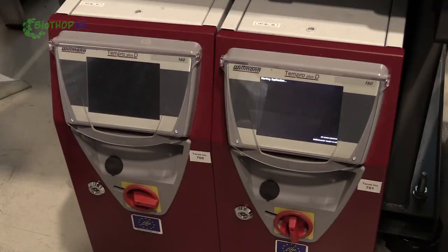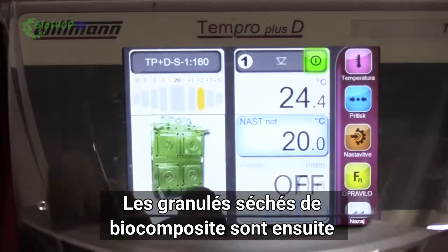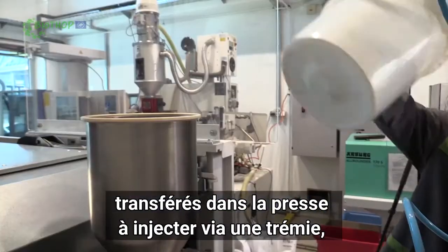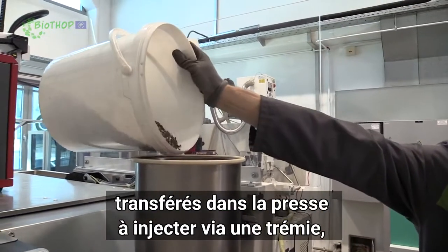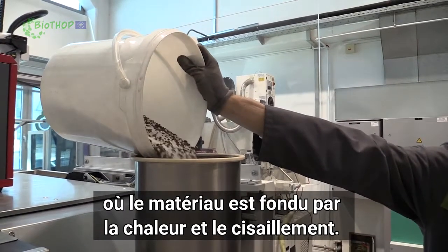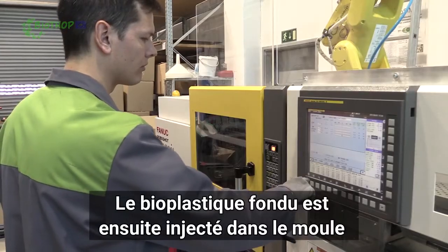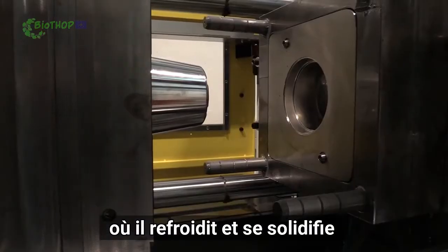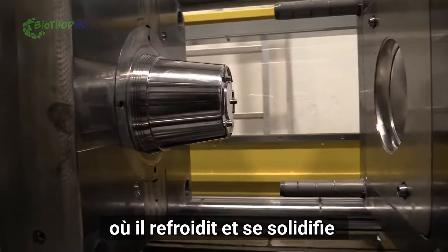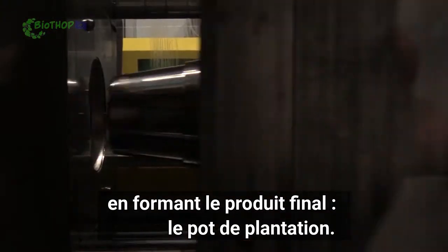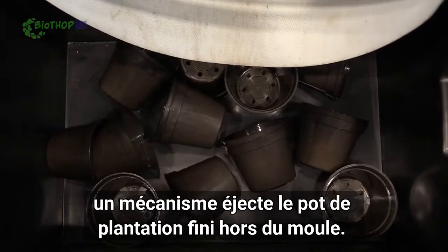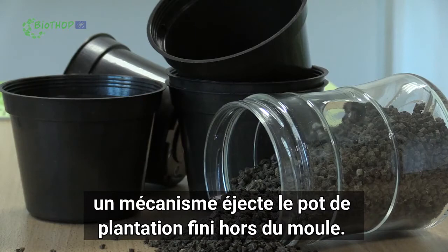The temperature of the mold is set to the required values on the tempering unit that is connected to the injection machine. The biocomposite dried pellets are then transferred into the injection molding machine via a hopper where the material is melted by heat and shear. The molten bioplastic is then injected into the mold where it cools and solidifies into the final part of the planting pot. When the mold is opened, an injection mechanism is used to push the final planting pot out of the mold.